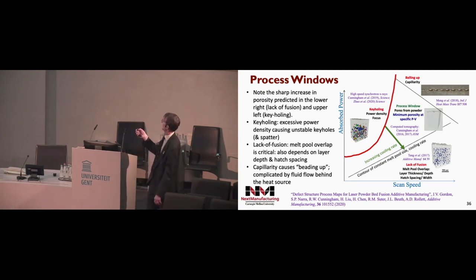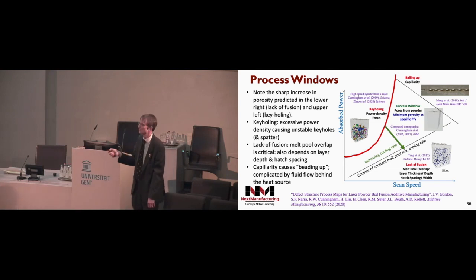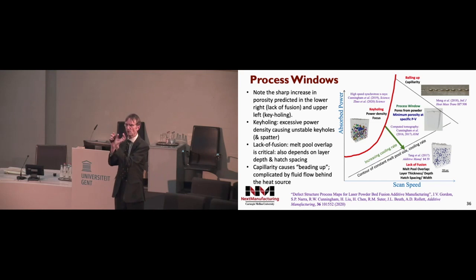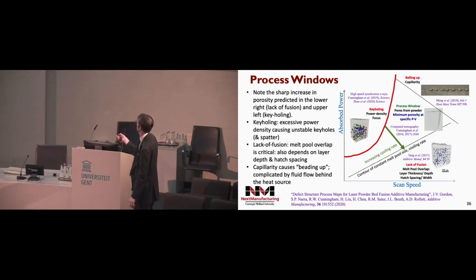So here you see a space of absorbed power versus scan speed. And we've drawn some lines on this. So the red line corresponds to what I was just showing you. If you're up and to the left, then that's a bad place to be. If you're down here and to the right, then your problem is that the melt pools are too small in relation to the spacing. And so you don't get enough overlap, and you are guaranteed to get lack of fusion porosity.